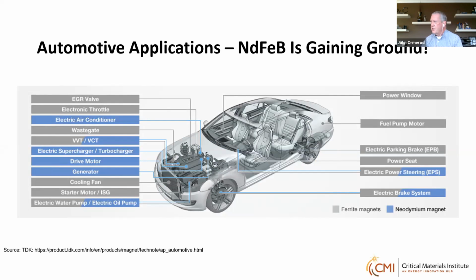But this is an interesting slide in that it shows, and this is from TDK, in blue, applications in the automotive market where neodymium-iron-boron magnets are now being used. You can see some of them are 100% neodymium-iron-boron, others are maybe 50%. And even more interesting, some of them are under-the-hood applications. So this is a trend that started within the last 10 years, maybe within the last 5 years, and appears to be accelerating. So a very interesting trend.